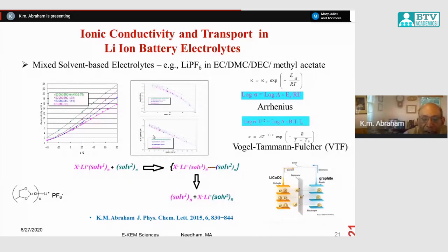From studying the temperature versus conductivity behavior of this electrolyte, we showed that the behavior is non-Arrhenius, and from that we were able to show that the ionic conduction is a solvent-assisted property. In other words, the ions move in the battery through the assisted motion of the solvents, because of the solvation of the lithium ion by the solvent.